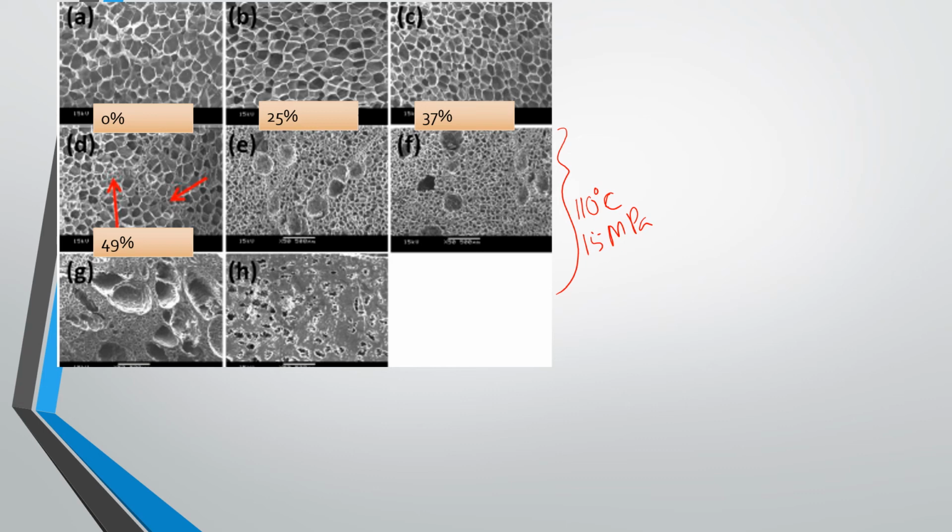Then when we move further to the increased nucleation, the next three pictures that we're going to talk about are E, F, and G. It leads to smaller bubbles alongside larger bubbles, as shown in 5E to 5G. And this also indicates that the cell density also increases since the diameter of the bubbles gets smaller. So as you can see, the diameters of the bubbles get lower as the size of the bubbles goes down.